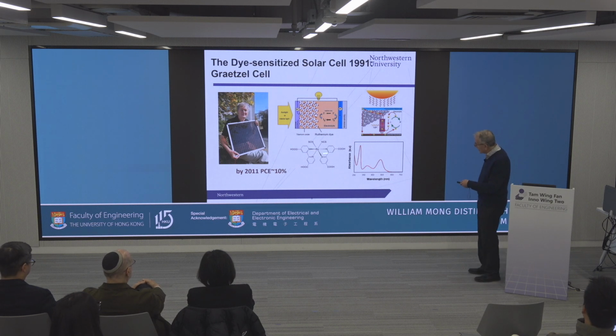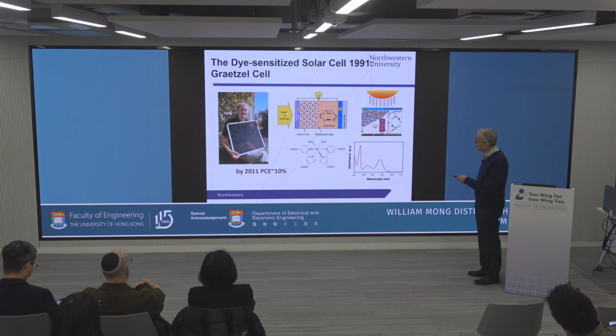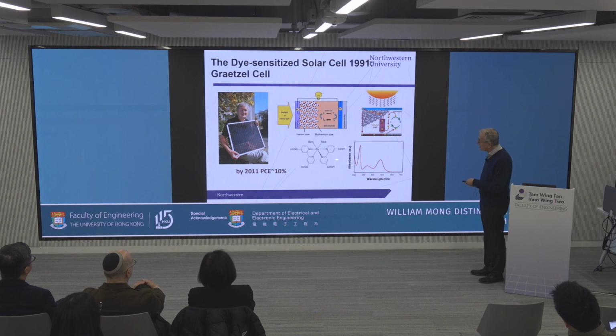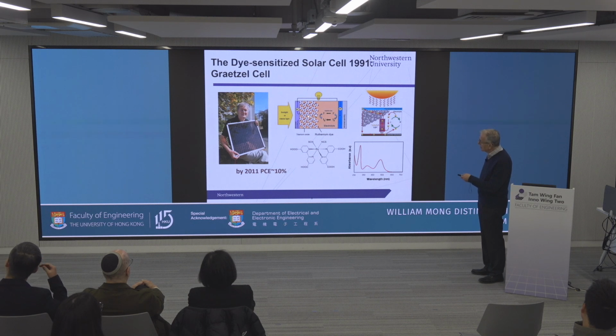And so when this gets excited, then the excited state pumps an electron into the TiO2 band structure. And then that one gets oxidized. The electron then can travel, which is miraculous in itself, going from nanoparticle to nanoparticle. This becomes oxidized. Now if you can reduce it, you recover it so you can absorb another photon. And then he used the iodide-triiodide couple dissolved in acetonitrile or DMF to actually reduce this material, make triiodide, take the triiodide to the other side, and then reduce it again and close the circuit. So this was transporting the hole, basically, to reduce that, and the titanium dioxide, the electron.